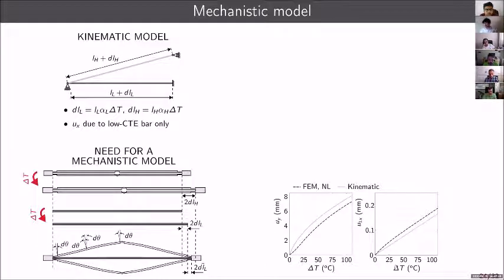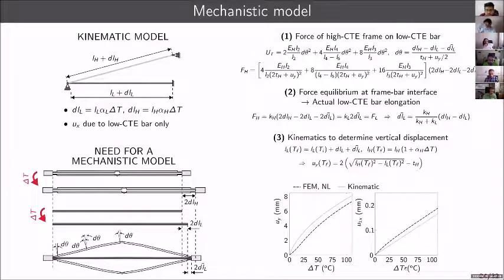So what we tried to do was to create a model that captures that. I will not go into detail. All we did was basically to try to figure out what is the force exerted by the expanding high-CTE frame on the low CTE bar, then do a balance of forces at the joints between low CTE and high-CTE material, and determine what is this additional elongation. And then use this additional elongation in a kinematic to determine the out-of-plane, the vertical deformation.